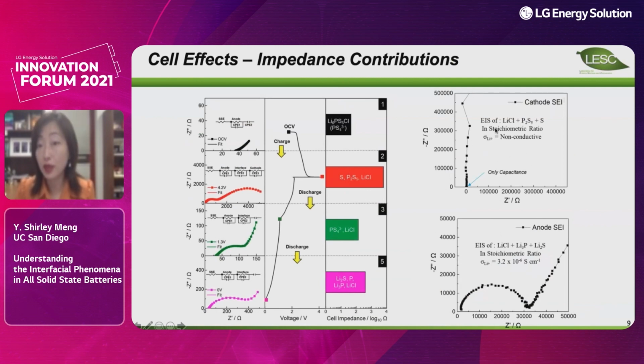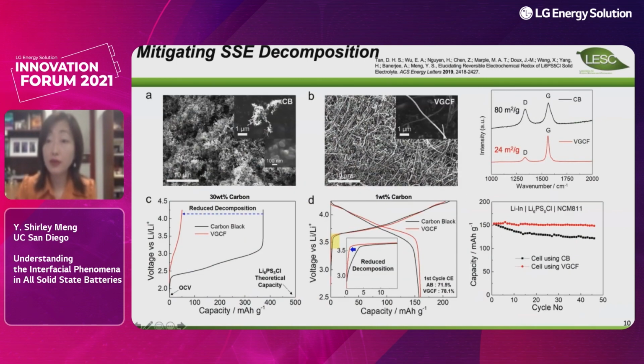So this is one of the obstacles we must overcome for cathode construction with the sulfide-based electrolyte. One effective way to overcome this challenge is to minimize the carbon contact with the solid electrolyte. As you can see from this set of experiments, if we replace the very high surface area, very conductive carbon black with an equally conductive but much lower surface area vapor growth carbon fiber, we can minimize the decomposition of the cathode, and then cycle the cathode NMC811 with the sulfide electrolyte.